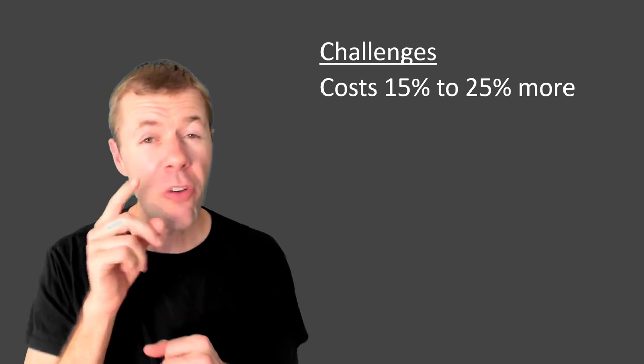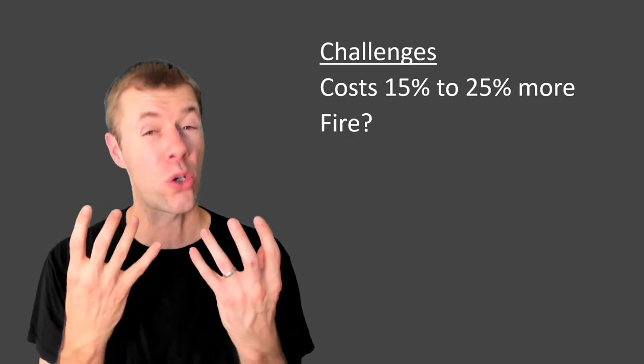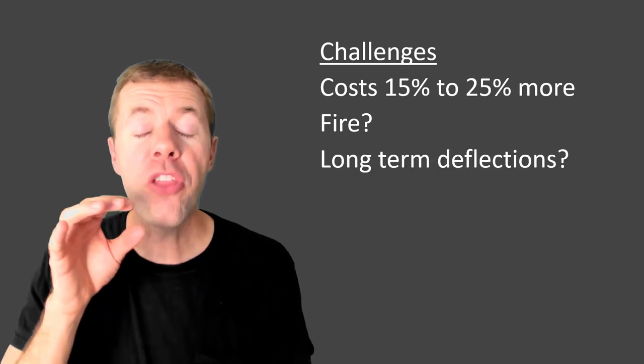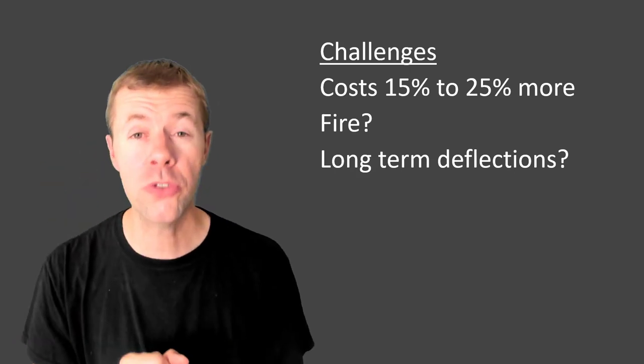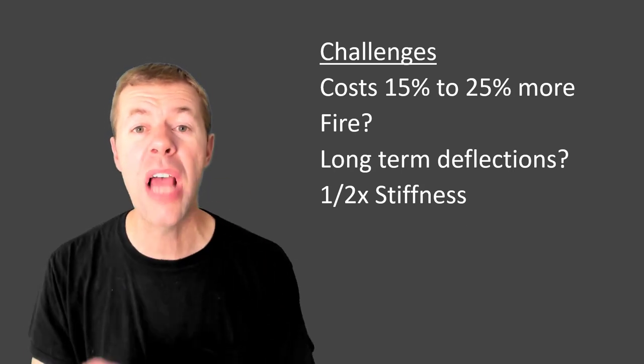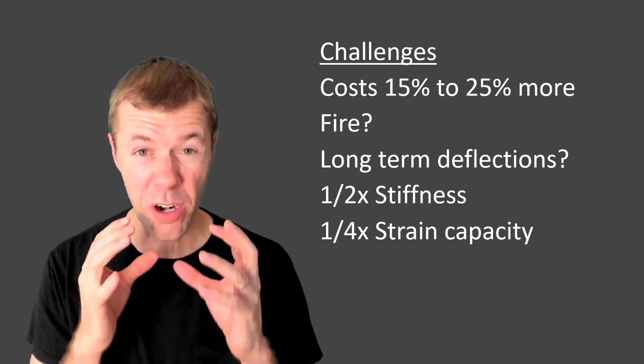Now there are challenges though. FRP costs more about 15 to 25% more. There are questions on how it performs in a fire. There's also questions about the long-term deflection or the creep of the bar. But the two things that I'm going to talk about that are most important is that the stiffness is about half of what a steel rebar is and the strain capacity is about one-fourth. Now these are very important.